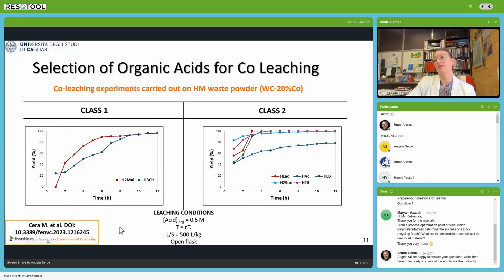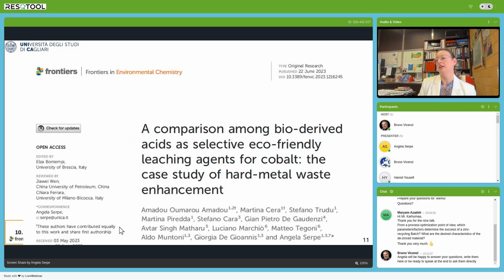And this is important because the presence of water when leaching tungsten carbide cobalt alloy can promote oxidation phenomena on the surface. So avoiding water can be an option for treating this kind of materials, avoiding oxidation on the surface. The studies on these different acids and their different behavior on cobalt are reported in a recent article that can be interesting for those more interested in the deeper chemical aspects.